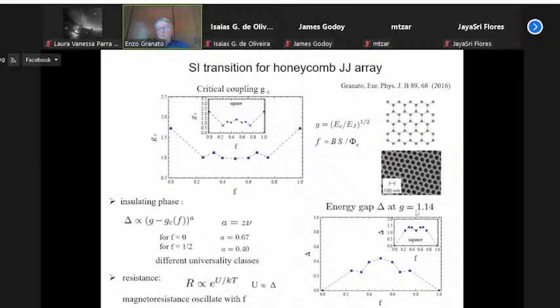Here we show the behavior of the energy gap, slightly below the critical coupling for zero field. You see that the energy gap increases and then decreases. There is no feature at 1/2. There is a feature at 1/3, which is what you see experimentally for the activation energy. There is an oscillation, with a maximum here and a minimum at integer values, but there is no minimum at 1/2. For the square lattice, you should see a minimum. But as far as I know, there is no experimental data obtained for the system yet.